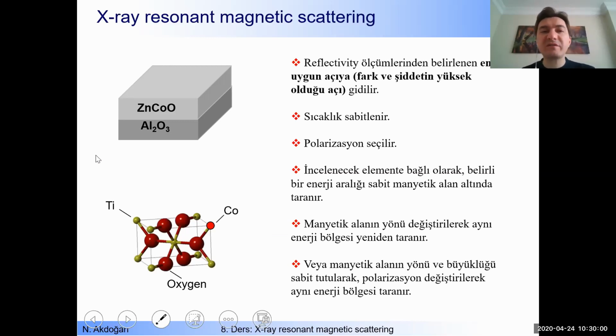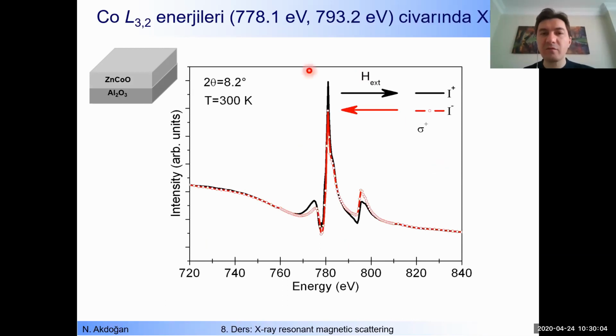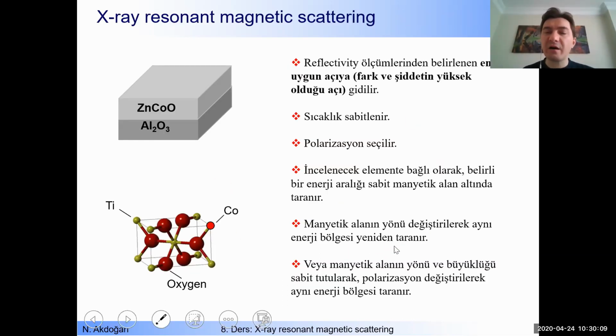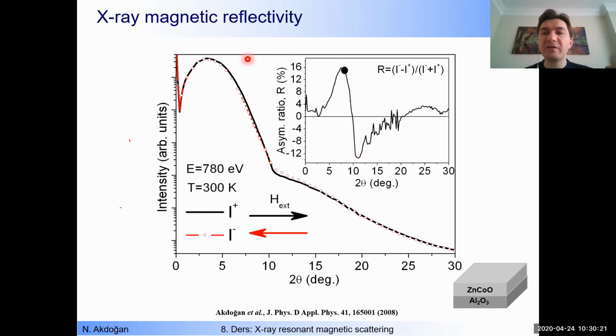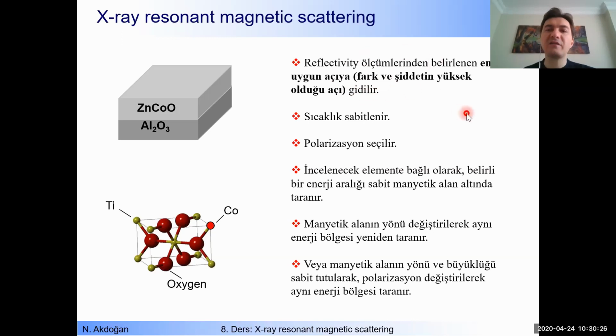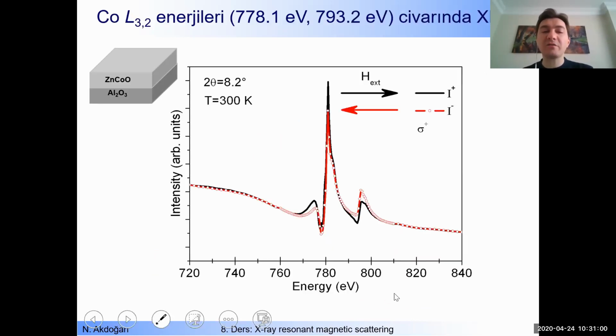So now let's continue with X-ray resonant magnetic scattering experiments. This one we will carry out. So how to carry out such experiments? First of all, just go to the best angle, which we determined from the X-ray magnetic reflectivity experiments, where the difference and the intensity are maximum, and then set the temperature, set the polarization, and scan the energy, like this one, energy in certain range. Then change the direction of the magnetic field, again scan that range, okay? And then another option is that fix the direction of the magnetic field, and then by changing the polarization, you can carry out same experiments.